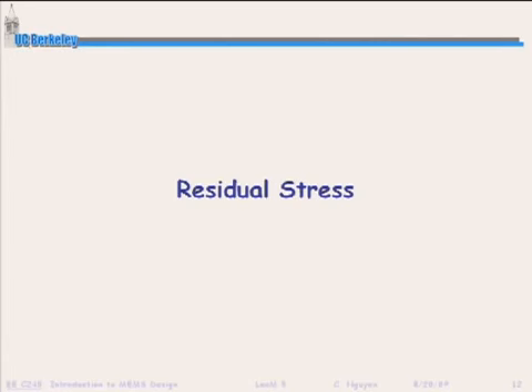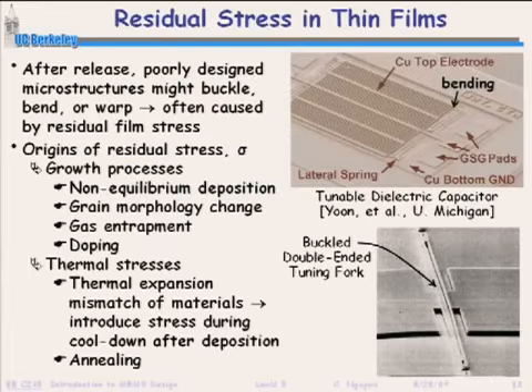So after release, if you haven't designed your microstructure well, or even if you've designed it well, but your process is not under control, structures could buckle, which is what's shown right here. So these are supposed to be beams that are perfectly straight, but that's not what you're seeing. You're seeing that they're bending out and into these, which are electrodes, and contacting these electrodes. They're not supposed to contact these electrodes. Okay, you can also have a warping of film. So you could sort of see here, this is meant to be a large tunable capacitor. It's held up by these springs, but look at what's happening to these springs. They're sort of warping out of the plane of the substrate, okay, which is not a good thing. And that's all happening because of residual stress.